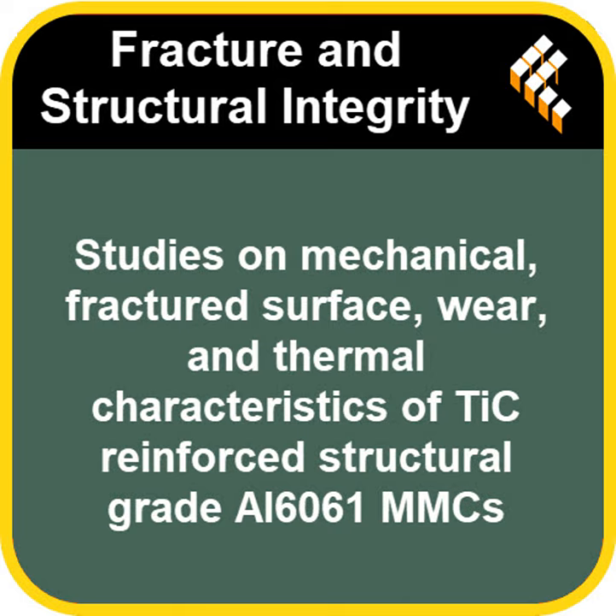They also observed very few tiny voids or gaps, what scientists call microporosities, and importantly, no significant buildup or agglomeration of reinforcing particles, especially in those lower to mid-range concentrations. So good mixing, few holes. You got it. And this successful uniform distribution and strong bonding between the TiC and aluminum was further confirmed by another technique, Energy Dispersive Spectrometry, or EDS. It basically verified the presence of all the expected elements, indicating a well-integrated material. Okay, so they successfully integrated these TiC particles without significant clumping or voids, especially up to a certain point.